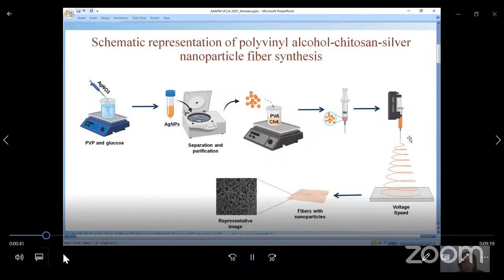Going ahead with the presentation, the first part includes the formation of silver nanoparticles, which was done through polyvinyl pyrrolidone and glucose, in which the silver nitrate solution was added dropwise, and further the separation of silver nanoparticles after their formation was done through a centrifugation process.